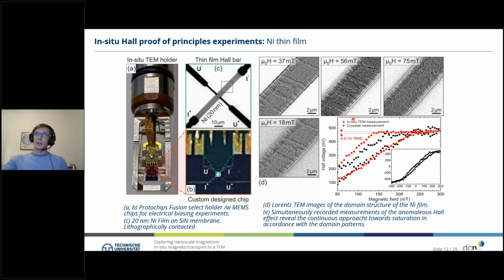And at the same time, we measure the Hall voltage, as shown here on the bottom with the red points. And we see that when we increase the magnetic field, we increase the Hall voltage up to the saturation. And then if we come back with the magnetic field, we see the hysteresis and the Hall voltage dropping down again. And if we have a look at the variation of the Hall voltage in saturation, we can learn something about the accuracy of our measurement. And from that, we see that we have an accuracy of roughly 6 nanovolts root mean squared for that measurement setup and the current we applied.